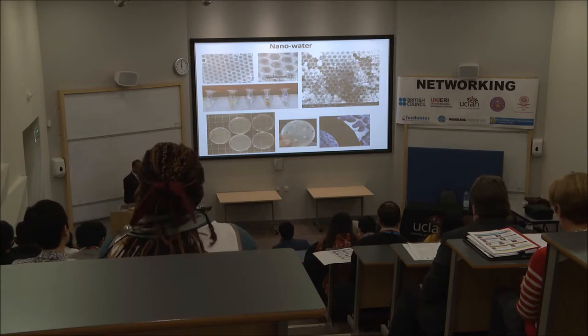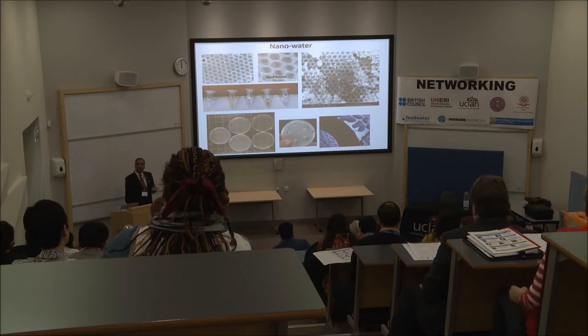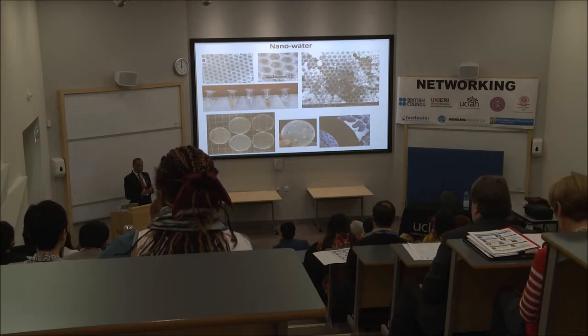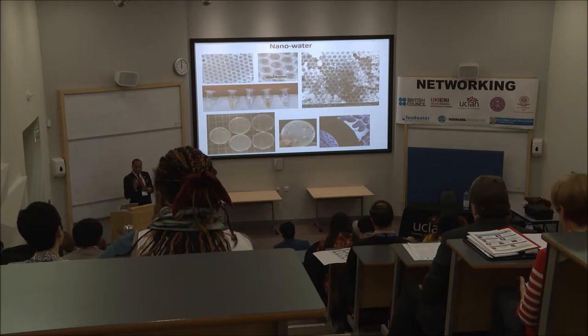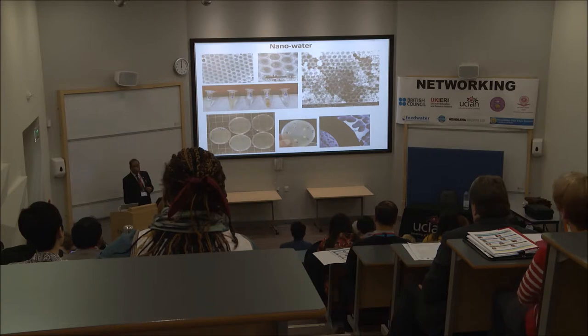In that project we developed powerful materials. The difficulty with the honeycomb membrane structures is that they are very unstable because of poor wall structures — they are amorphous and collapse under high temperature hydrothermal conditions. So we came up with the idea of using nanocrystalline zeolites to build the wall structure of those honeycomb structures. Zeolites are industrially applicable for petrochemical refining and also for water purification because of their powerful ion exchange properties.